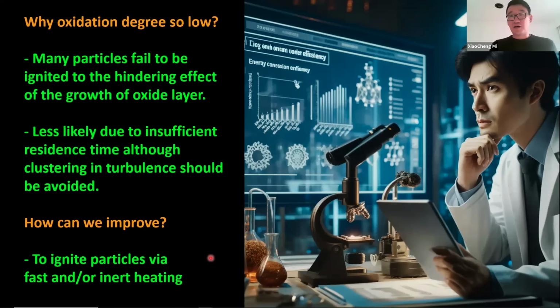Turbulence-caused clustering can elongate the combustion time a little bit, but not make it longer by one order of magnitude. So it's still on the order of tens to maybe 100 milliseconds, which is very short. So what we can improve, I think the main thing that we need to do is make sure the ignition rate is as high as possible.